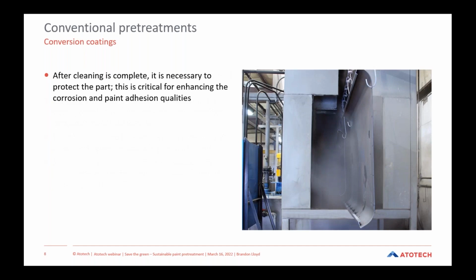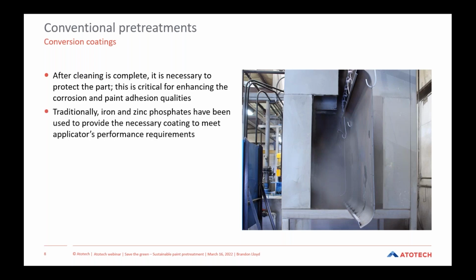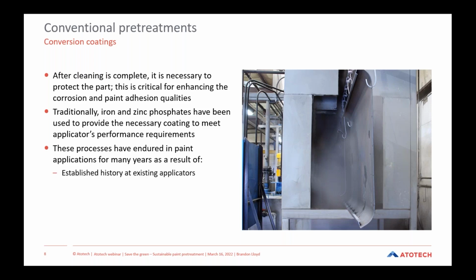Looking at conversion coatings, so after the cleaning process itself is complete, it is of course necessary to protect the part. And this is critical for enhancing the corrosion and paint adhesion qualities of the final production parts. Traditionally, applicators have implemented iron or zinc phosphates, and they have been used to provide the necessary coating to meet applicators' performance requirements. These processes have endured in the paint applications for many years as a result of several factors. They have a well-established history at existing applicators. They're written into existing specifications. This is especially true for automotive industry as well as construction and agricultural equipment. And they are relatively easy to use.